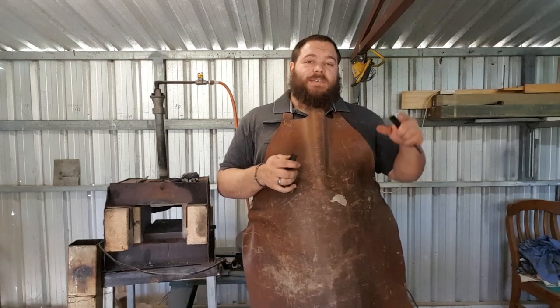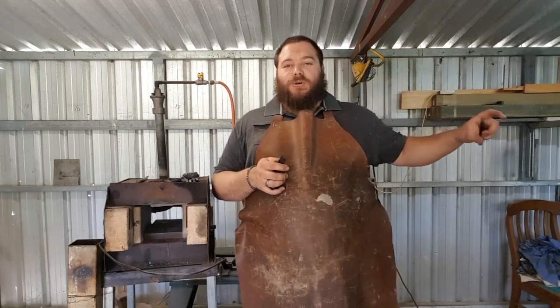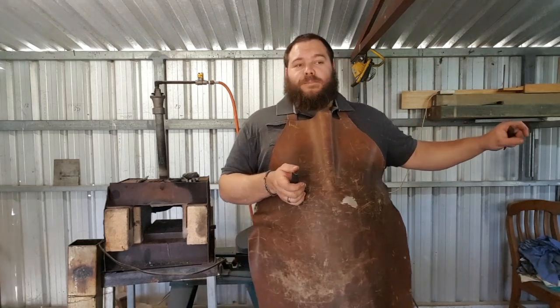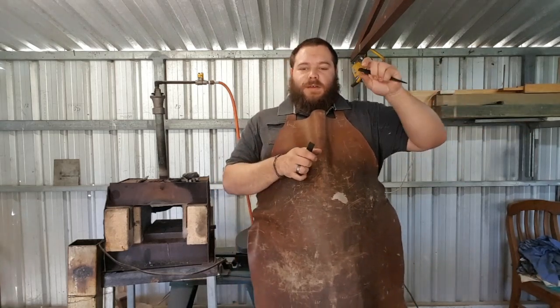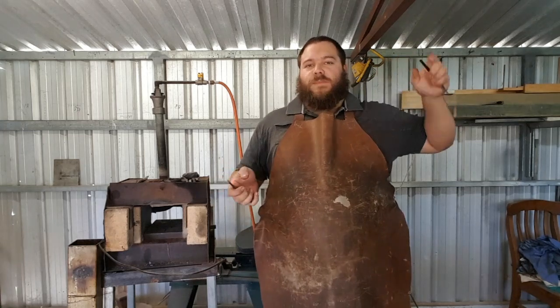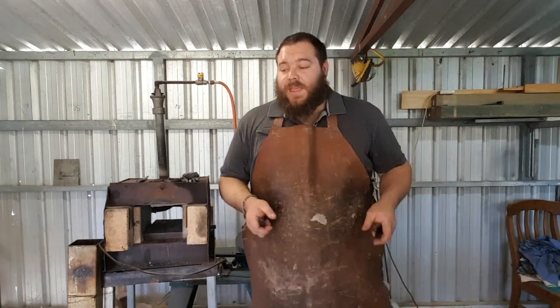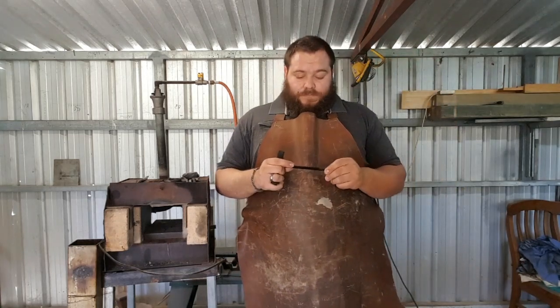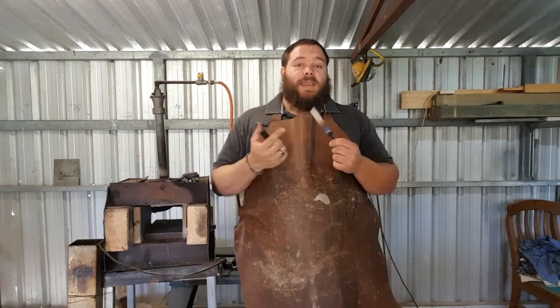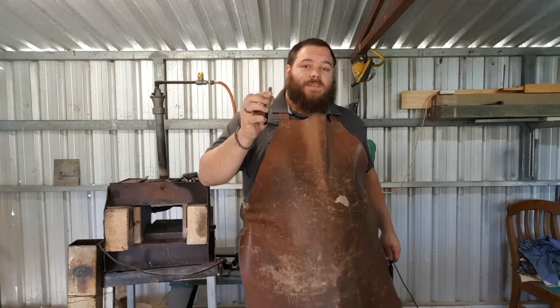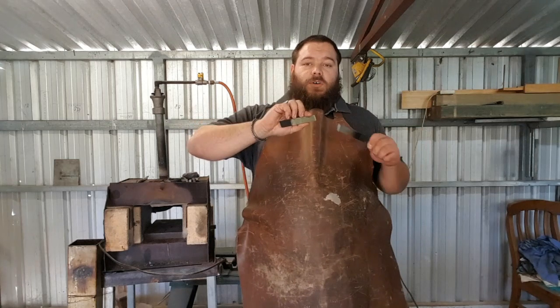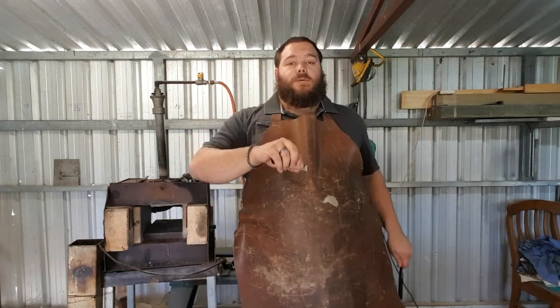And I've actually seen blades that the quenched portion had snapped away from the unquenched portion because the line of ferrite and the unchanged austenite has ripped away from the martensite that's formed. So that can be dangerous. Whereas tempering back from the spine is a really good way to go. Actually, on large knives, I tend to quench fully, oven temper, and then sit the edge or the area that I don't want to be tempered in a bath of water, and then temper the spine back with a torch.